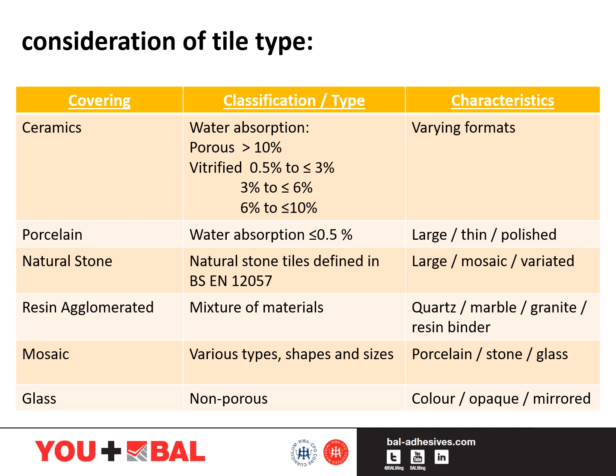For information, dispersion or ready-mixed adhesives are only suitable for use with porous bodied wall tiles or ceramics, but not porcelain in general. Use highly polymer modified cement-based adhesives when fixing porcelain tiles to walls and floors.